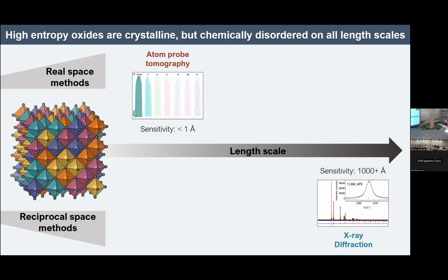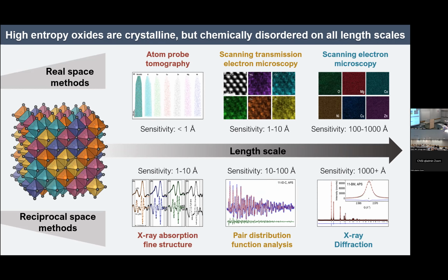We can also look at a very local length scale with a technique known as atom probe tomography, where the material is fabricated into a tip, and atoms are evaporated off the end of that tip, and we can reconstruct through time of flight mass spectrometry a 3-dimensional image of where the atoms in that material were located. When we do atom probe tomography on a high entropy oxide, you might be able to see these very faint speckles, all overlapping each other on this leftmost image. The point I want you to gather is that the positions of those atoms, marked by the colored pixels, are not separated or clustered. They seem to be, at least to a first approximation, randomly distributed throughout the material. So we have these 2 requirements: random chemically, but crystalline on average. And this picture is reinforced at every length scale. We can look with different electron microscopy techniques, as well as pair distribution function. In every case, we see a picture consistent with what I've just told you.